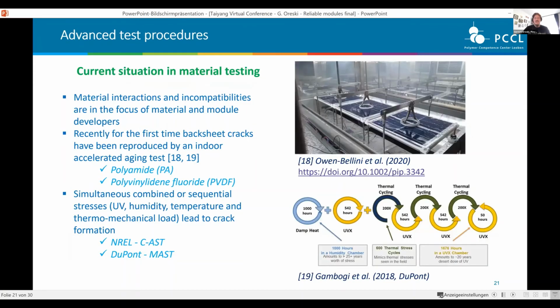That's a big thing that has changed in the recent years. The awareness that you need to do this test to replicate certain failure modes. And I think just to point out the most prominent initiatives. So one is from NREL in the US, Denver. They have this combined accelerated stress test. The other one is developed by DuPont, this MAST test, which is a sequential stress test. And both of them actually could reproduce the cracking of the backsheets. Not only the polyamide backsheets, but also, for example, PVDF backsheets, which is quite prominent.